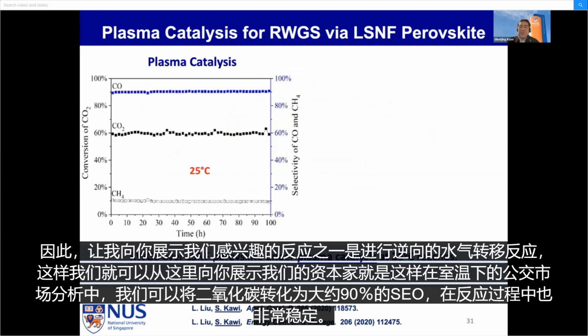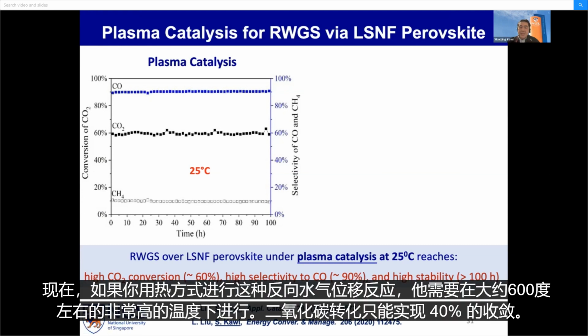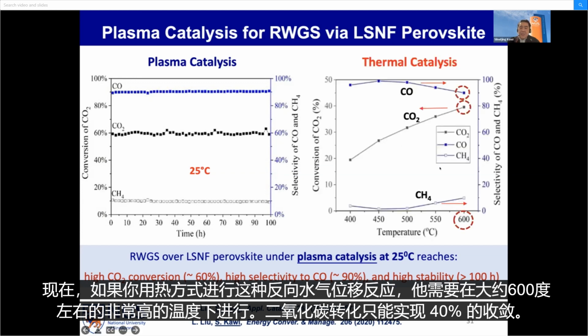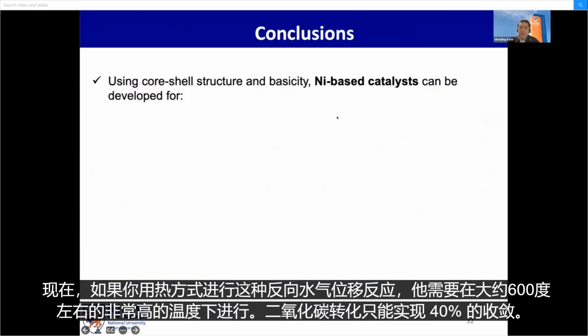So let me show you one of the reactions that we're interested in, which is the reverse water gas shift reaction. I can show you from here that with our catalyst during plasma catalysis at room temperature, we can convert the CO2 at around 60% to produce a very high amount of CO, about 90%, and it is also very stable during the reactions. Now, if you do this reverse water gas shift reaction thermally, it needs to be done at very high temperatures. At around 600 degrees, the CO2 conversion can only achieve 40%.